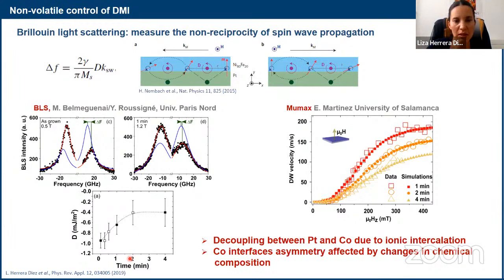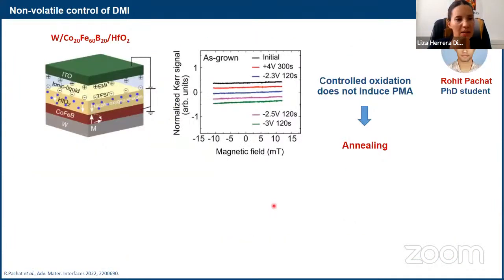So I think I'll go a little bit faster here so I can reach the last part. Once again, it's interesting to look at ferromagnetic layers that are on top of heavy metal substrates. So here we have cobalt iron boron on tungsten. And what we find here is that we do the same experiments as I showed before. We apply the voltage to our ionic liquid, but we don't find anything. Neither positive nor negative voltage would do anything to this sample.